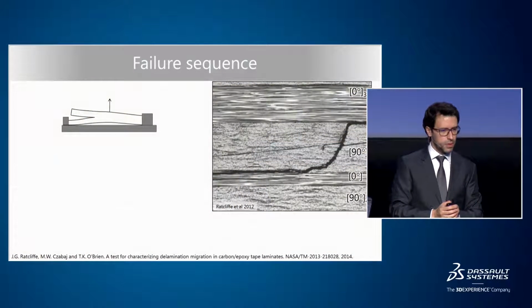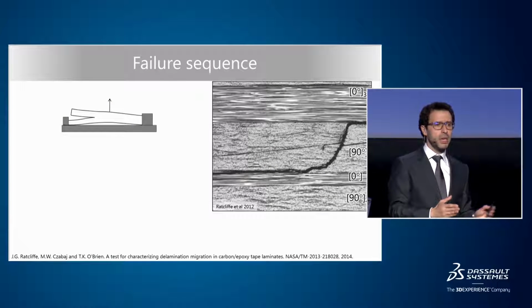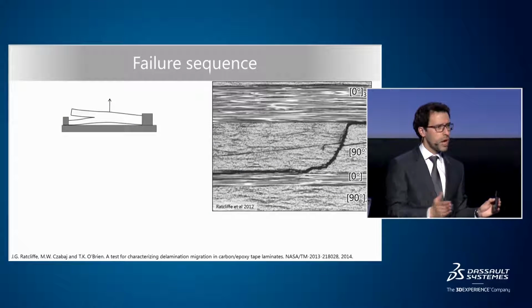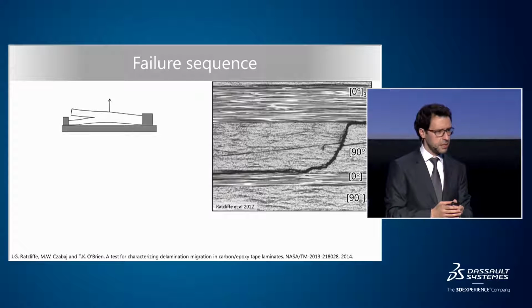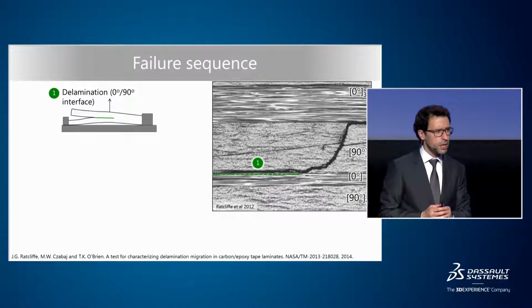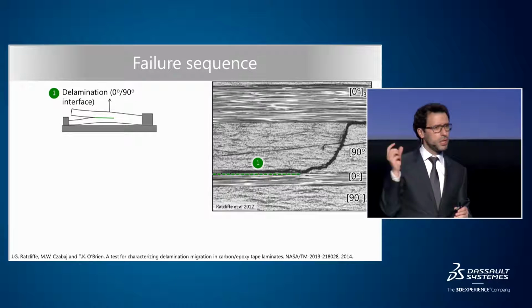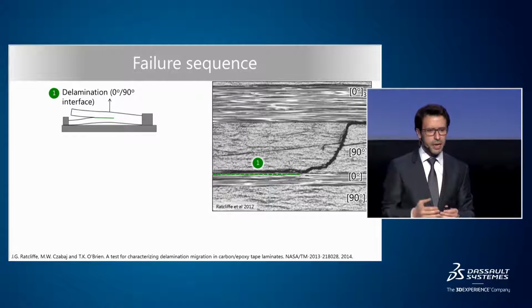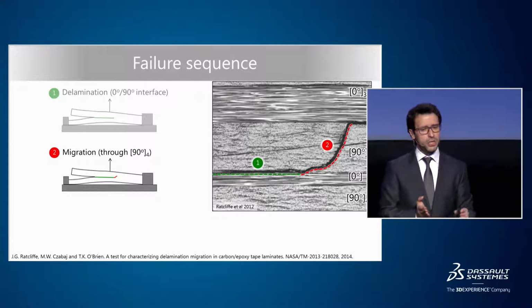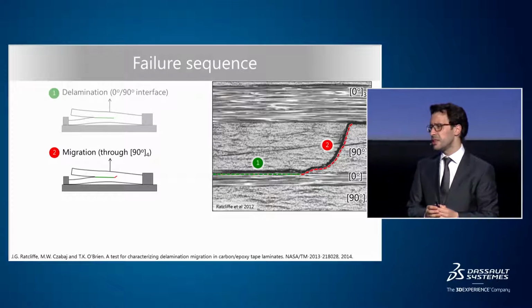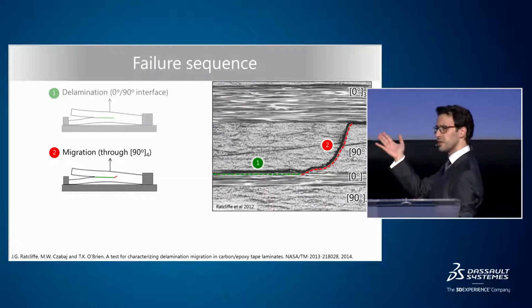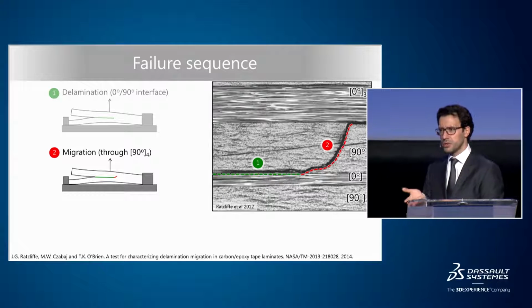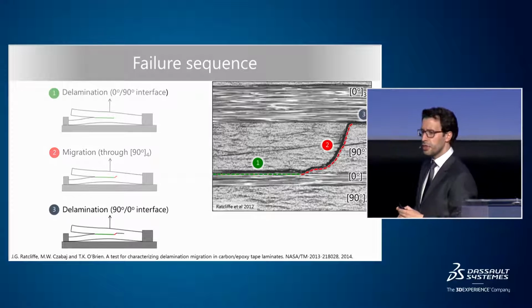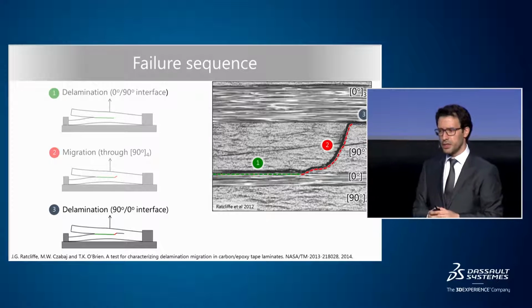So I have now some drawings that allow you to see that. At the beginning, the diagram shows the initial crack that you have in your specimen before the crack starts growing. Then as you increase the load applied, the crack grows in the position in green as shown, in an interface between a 0-degree ply and a 90-degree ply. Then after it has grown for a certain amount of time, the crack changes direction and migrates through this 90-degree ply in a shape which is not a straight change, so you have a curvature there. And then thirdly, the crack continues in the different interface.